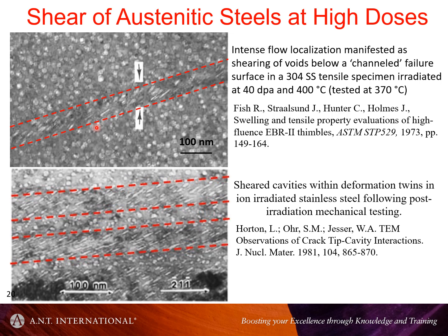So the very fact that even in a channel you have dislocations which climb as they sweep up the loops, and then they're going on various possible planes, that's the reason why we end up, even with a channel, perhaps with a bulk shear, but this could also be a twin. And actually, if it was two twins, you would not see the outcome.